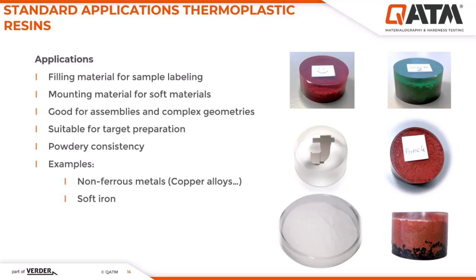In addition, fully transparent mounts can be produced using thermoplastics, which is especially used for soft materials because thermoplastic resin is very soft. So assemblies or complex geometries or soft materials can be mounted with thermoplastic resin. These mounts are particularly well suited for target preparation because of their transparency. Thermoplastic mounting material is available as a fine-grained powder. Typical examples of soft materials that can be mounted with thermoplastics include non-ferrous metals like copper alloys or soft iron.